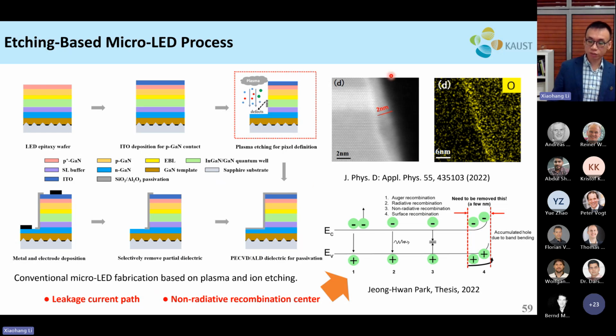And then, this image is very nice. It illustrates that the sidewall actually has a couple of nanometers of highly amorphous layers. And those layers will trap your electrons and holes and also become the non-radiative recombination centers.